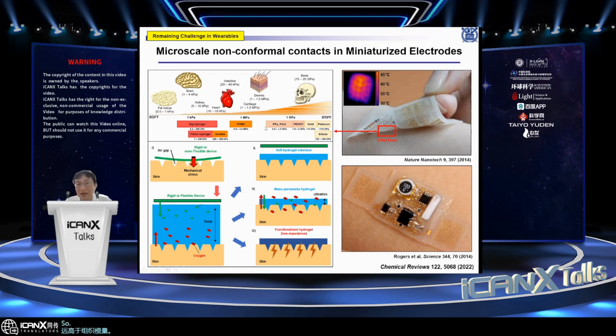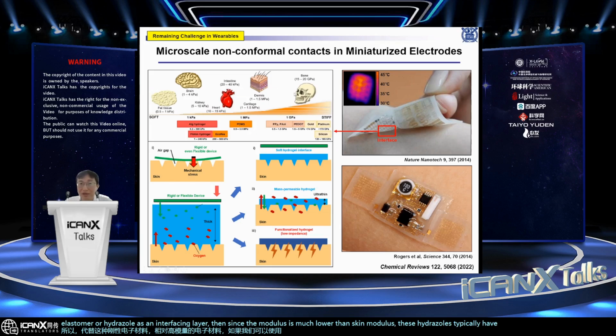So instead of this rigid electronic material, relatively high modulus electronic material, if we can use soft elastomer or hydrogel as an interfacing layer, then since the modulus is much lower than skin modulus, these hydrogels typically have tens of kilopascal modulus, which is lower than skin modulus. So these air gaps can be completely filled with the soft material. In addition, if we can add some conducting fillers to this soft material like hydrogel or elastomer, then for the contact impedance, first of all, we can make very good conformal contact to the skin, so the contact area can be large.